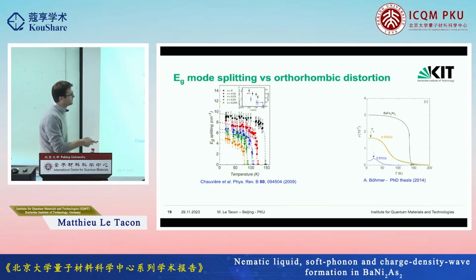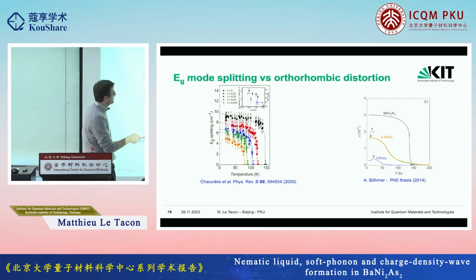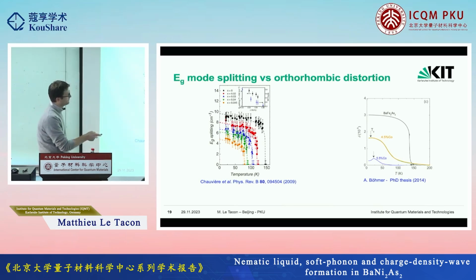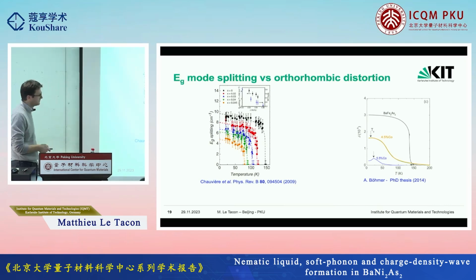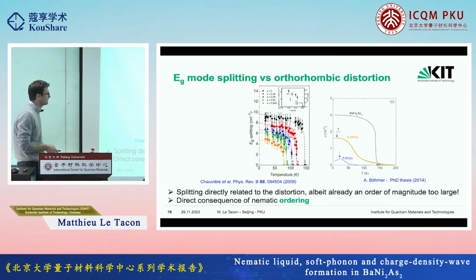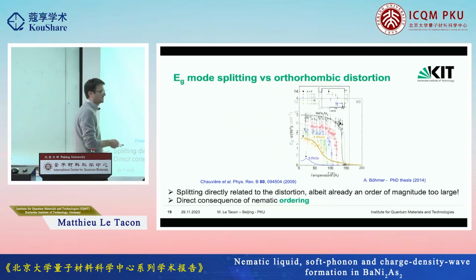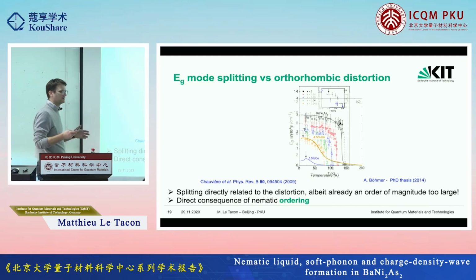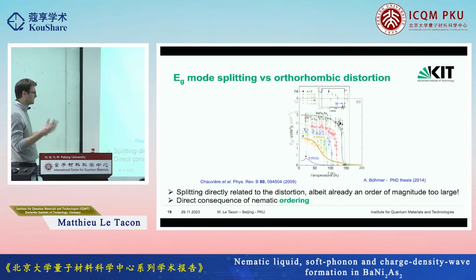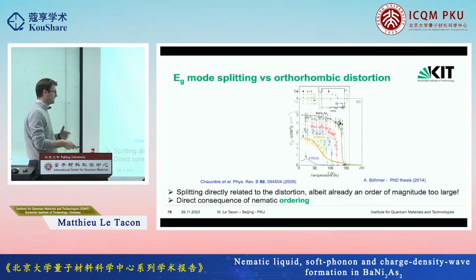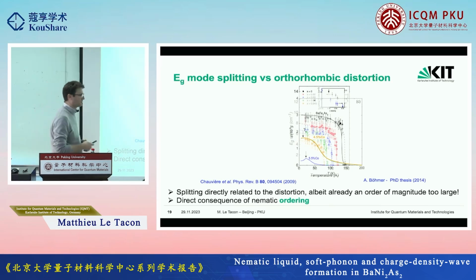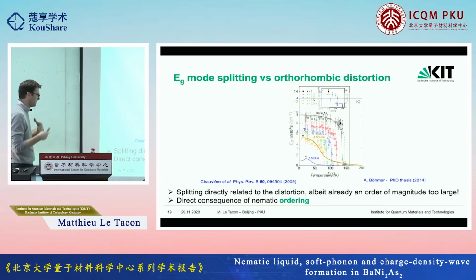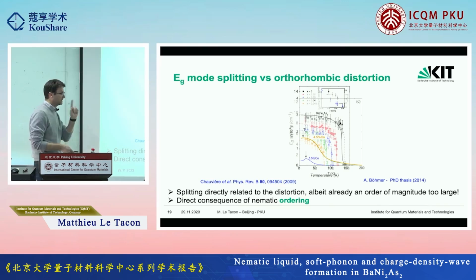And she did dilatometry also on this compound, and I actually use this thing, and you can scale. So you get the parent compound, the 4.5% and the 5% cobalt-doped system. And you can translate these two things one onto the other, and you can basically see that they match very well. So the phonon splitting really is, in that case, a measure of the orthorhombic order parameter, or said otherwise, of the nematic order. Nematic order, I insist on that.